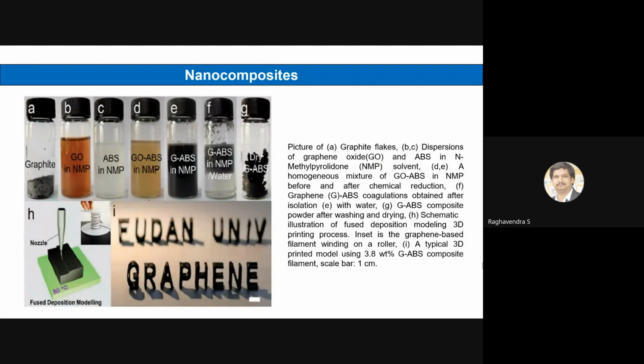So this is one example where you can see how this method works, or how you can prepare that composite. In the picture, the first one is graphite flakes. B and C are what you get if you disperse graphene oxide and ABS in a solvent. Here the solvent used is N-methyl pyrrolidone. You can see how that solution looks in B and C, and in D and E you create that homogeneous mixture of graphene oxide and ABS in NMP, before and after the chemical reduction. F is where the graphene ABS coagulation is obtained after isolation with water, and finally if you wash and dry that, you will get the composite powder.